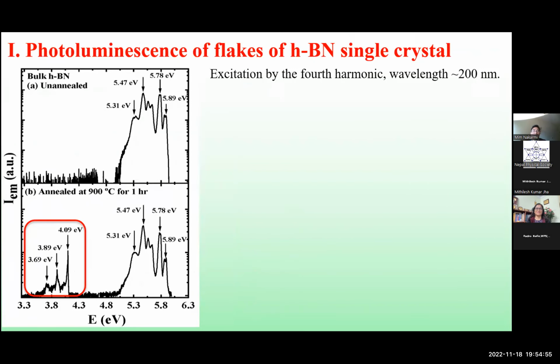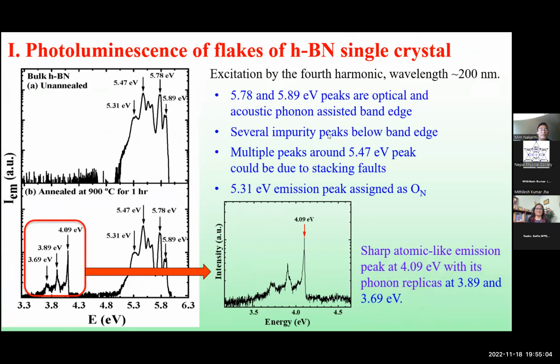So here is our result on hexagonal boron nitride. The upper one has many emission peaks, and each peak is related to some energy level, which we have to explore. What we know so far is that these peaks, 5.78 and 5.89, are not from band to band, because it is not a direct band gap material. They are emitted with the help of phonons. So these are optical and acoustic phonon assisted band emission.